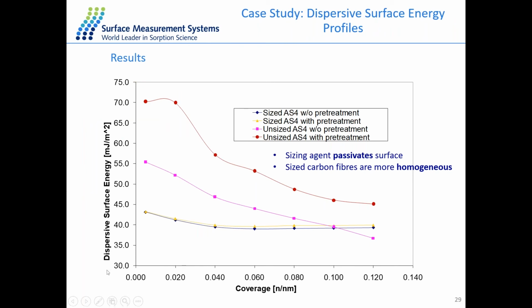So this plot is looking at the dispersive surface energy with increasing coverage. What we can first see here is that our sized material compared to our unsized material has a lower dispersive surface energy. Our unsized material has a much higher surface energy, especially at this region here, the infinite dilution region. And this is suggesting that at small concentrations, we're able to access higher energy sites, which are only available in the unsized carbon. But once we increase the injections over higher surface coverages, these tend to plateau out. So this is suggesting that the unsized material is much more heterogeneous compared to our sized material.